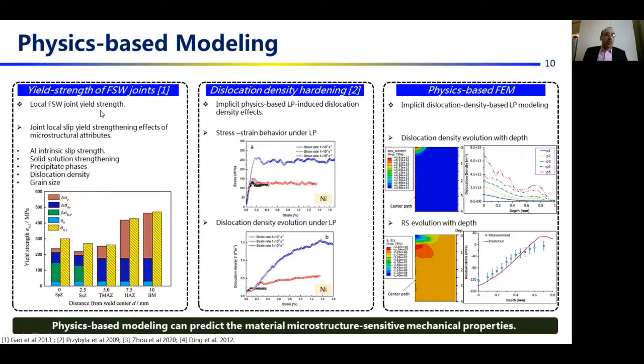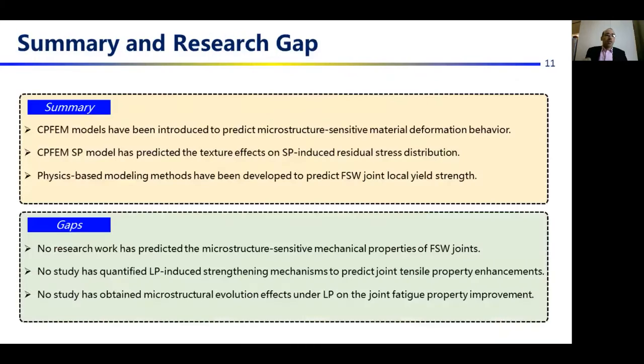Physics-based modeling has been developed previously to predict the local yield strength of aluminum lithium FSW joints. Moreover, the strain gradient physics-based modeling methods have predicted the dislocation density-based hardening for the stress-strain behavior of material under laser peening and the resulting dislocation density evolutions and the residual stresses under laser peening. To summarize the literature, CPFEM has been introduced to predict the microstructure-sensitive material deformation behavior. CPFEM shot peening model has predicted texture effects on the shot peening-induced residual stress distribution, and physics-based modeling methods also have been developed to predict the FSW joint local yield strength.